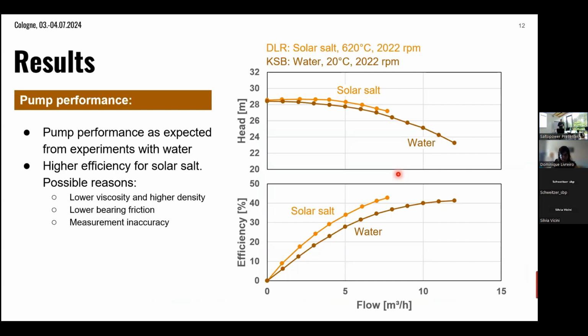Okay. So the first result I show you is the pump characteristic curve for water and for molten salt at 620 degrees. And we see from the slides or from the diagrams that the pump characteristic curve is similar for molten salt as for water. The difference might be explained due to differences in the viscosity and also the density. The same applies for the efficiency. So for the solar salt, we have a slightly higher efficiency than that we measured, or KSB measured with water. And it might also be that there are some measurement inaccuracies, but this is probably not the biggest.